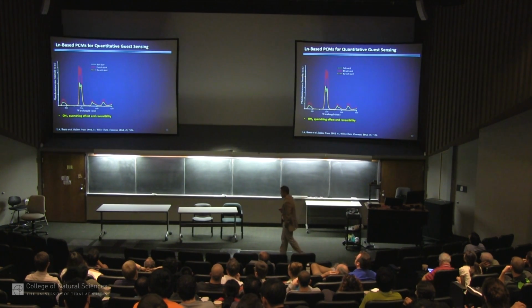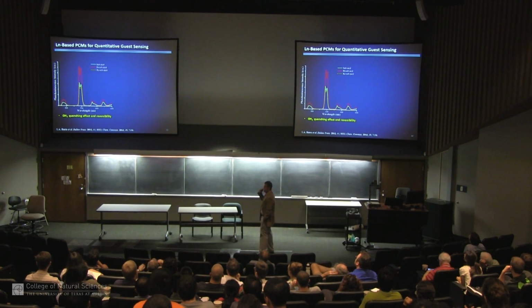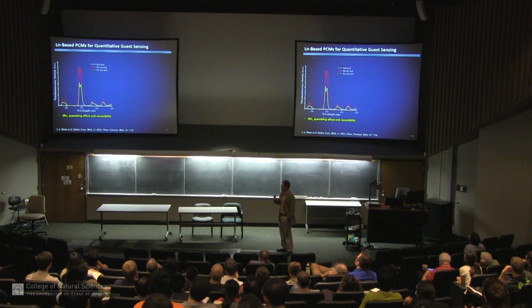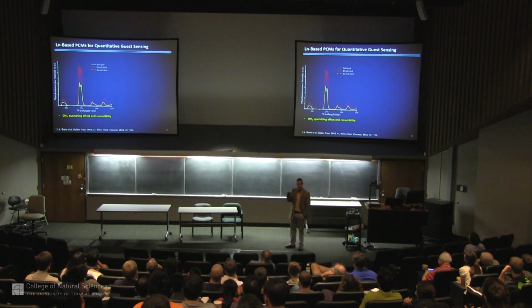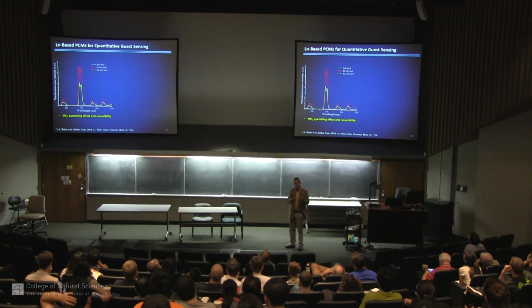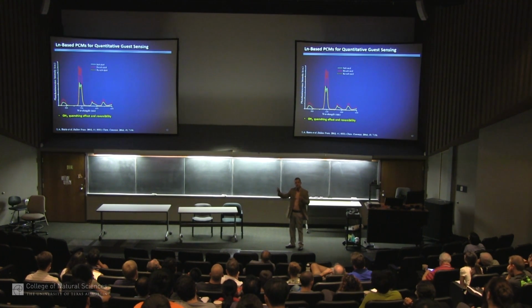And if you look at the luminescence of this material, and this is because the terbium itself is emissive, you can actually monitor which state of the material you're in. Now I have to explain a little bit quickly about the luminescence here, not in too much detail, but these materials are strongly luminescent because the phosphine ligands themselves that make up the walls of the material absorb light. They get to an excited state. They transfer the excited state energy to the lanthanides, which are also within the framework. The lanthanide is now excited, so it's been indirectly excited, and it luminesces.